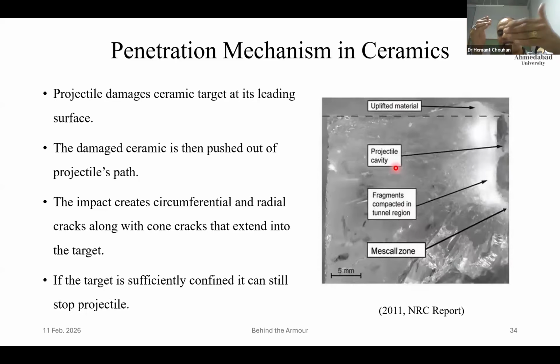Then because of the high linear velocity and high hardness of the projectile, a high hardness material will always break into two instead of getting a ductile deformation. Ceramic will make sure that along with the damage of the ceramic, the projectile is also broken. Once your projectile is broken into more than one part, you are going to handle multiple pieces, but thankfully at a lower kinetic energy, because the initial kinetic energy was a constant number. Now it is broken down into multiple pieces. So handling becomes both easy as well as difficult.